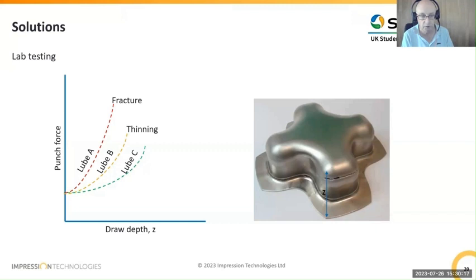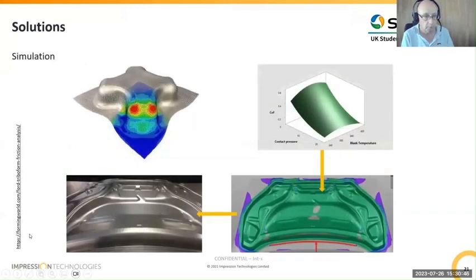But with the best lubricants, we don't see any thinning, we don't see any splits. They go to the full depth of draw, and they give us the lowest loads that we record on that information. And we can then chop these parts up and measure the thickness of the material, as I said before, so we can then pass that information back to our simulation team. So they take that data and generate simulation equations and run those under various speeds and loads and material thicknesses, and eventually they come out with a prediction of what we actually see in the lab, and then transmit that information along with contact pressures, blank temperatures, and so on, and coefficient of friction.